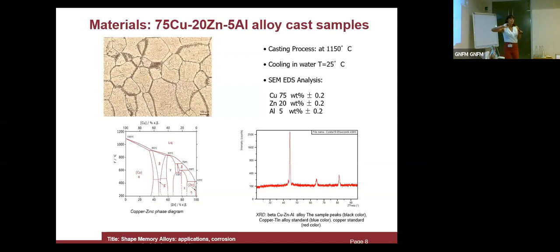Okay, so we focus our attention on a copper, zinc, aluminum alloy with 20% of zinc and 5% of aluminum. We produced this alloy in the laboratory at the Department of Chemical Engineering, thanks to the support of Engineer Brozzo and Professor Natali. And we cast our bronze ingot at 1150 Celsius. Then we cool the ingot to 25 Celsius degrees, and then we analyze it.